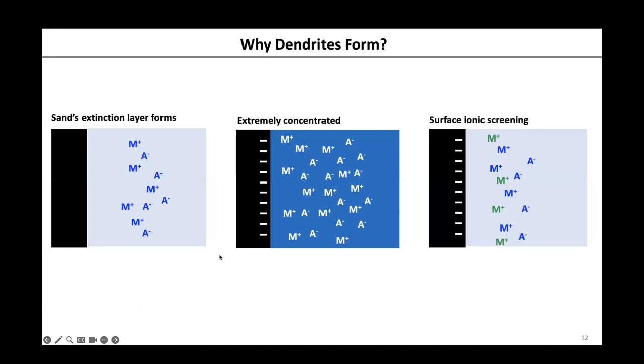All right, so what is the mechanism for dendrites to be formed? It is related to a well-known phenomenon called the Sand extinction layer. If you have plating going on, your electrode or current collector is negatively polarized. You're going to have an excess of electrons on the surface of the metal, and that attracts cations, which are converted to metal. Because the surface is negatively polarized, it repulses the negatively charged anions away. You're consuming cations and pushing anions away, so you generate a vacuum of ions near the surface of the electrode or current collector.